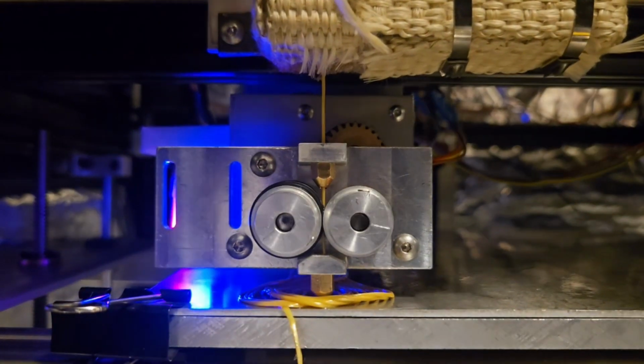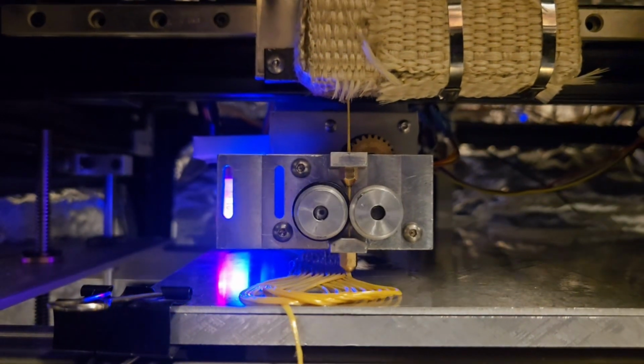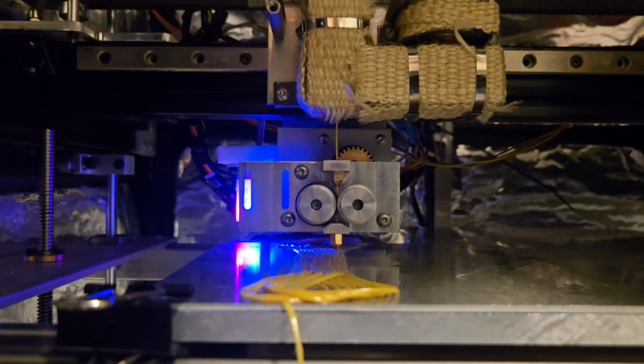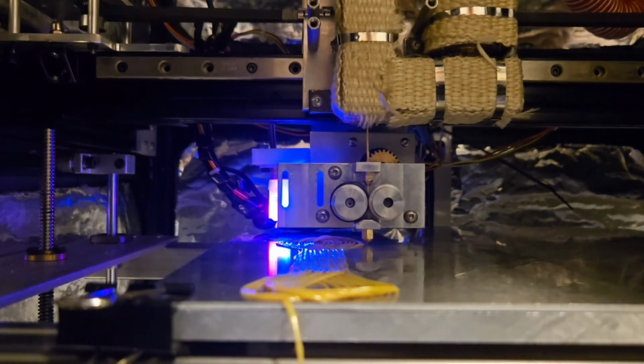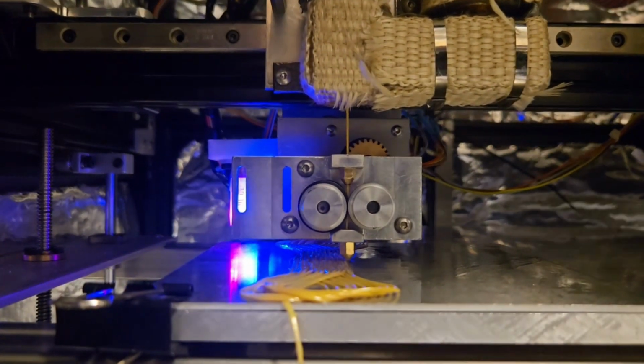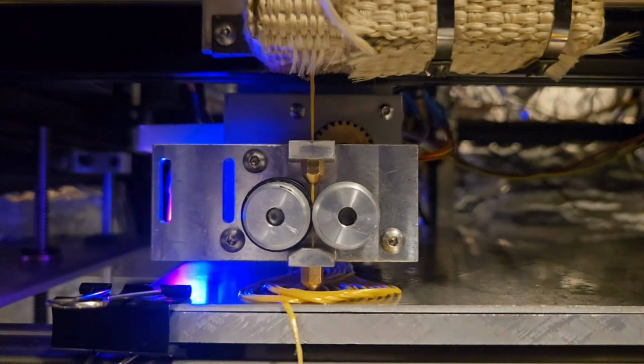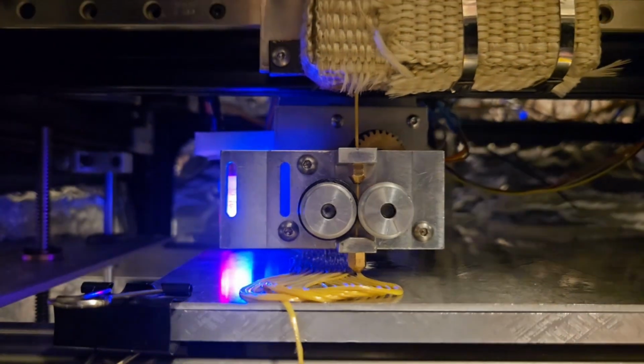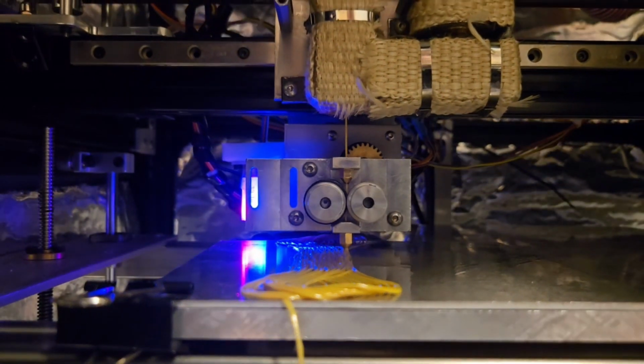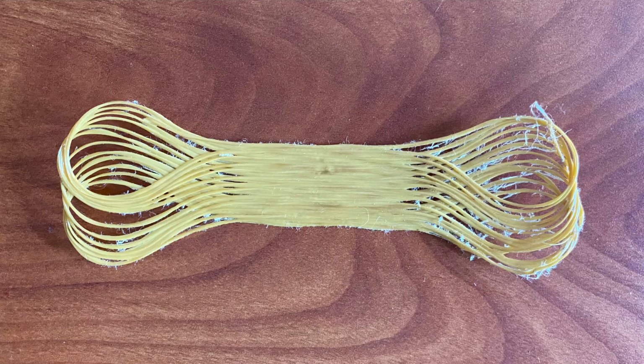Once we found the ideal printing parameters, we then decided to move forward by making a full print sample. Then, once our coding path was done, we printed a sample. This was a huge success, especially since we were the first group in this whole legacy line of groups to achieve this, but we weren't done yet. From here, we sent the sample through a post-processing stage and we achieved a fully cured sample.